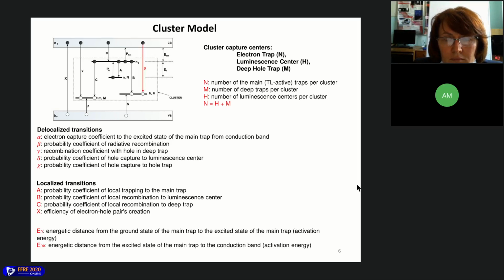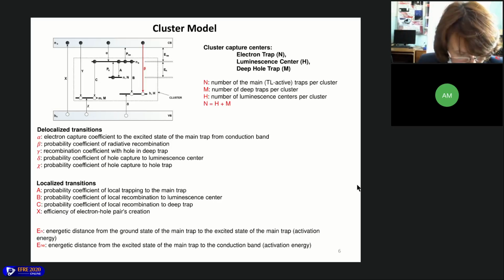The main difference of the introduced model is the presence of deep hole traps along with the luminescence center inside the cluster and corresponding transitions. Each cluster contains the same number of electron active traps N, luminescence center H, and deep hole traps M. We assume that number of electron traps is equal to the sum of both luminescence centers and deep hole traps. The restriction is based on assumption that such cluster is more stable due to Coulomb attraction between defects of different charge state.